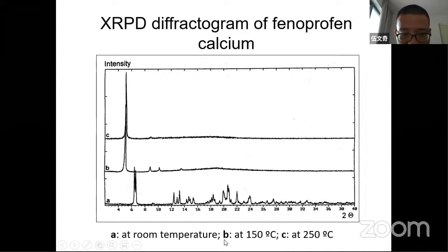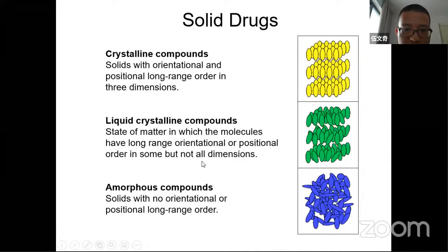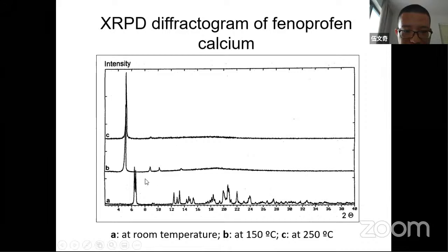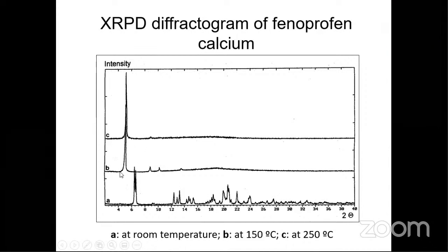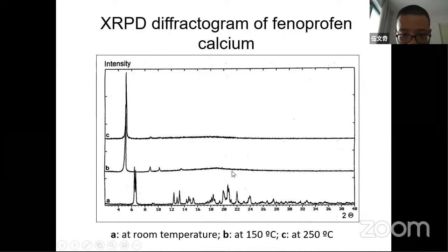From Figure A, at room temperature, this is a crystalline compound showing very sharp peaks. Figure B, at a higher temperature, is kind of like a liquid crystalline compound, between A and C - sorry, B is the liquid crystalline compound. Figure C, at higher temperature, shows no long-range order, at least from 10 to 30. So using this technology, we can see a lot of information about these compounds.